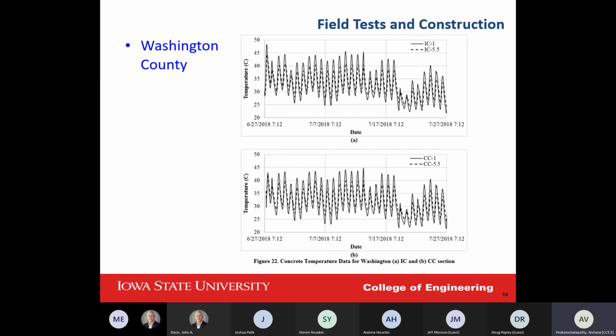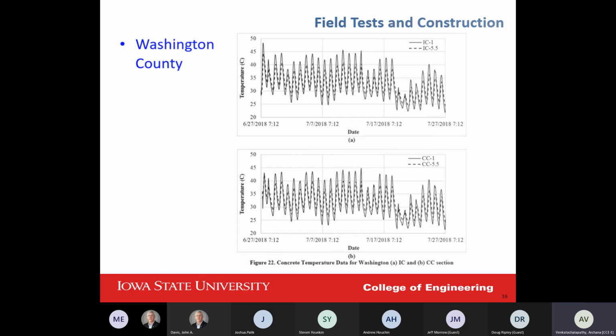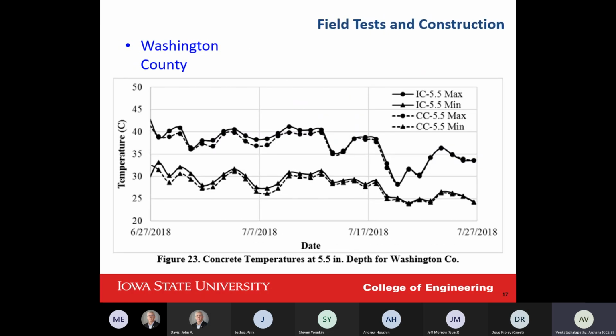So this is kind of a messy one, but just a big picture of the whole temperature that we measured. If we want to get into more detail, I tried to deduct the temperature numbers of the bottom from the top of the concrete. So we measured the max and min temperature per day at a depth of 5.5 inches in both layers. In the internal curing, we can see the max and min getting closer after 28 days.